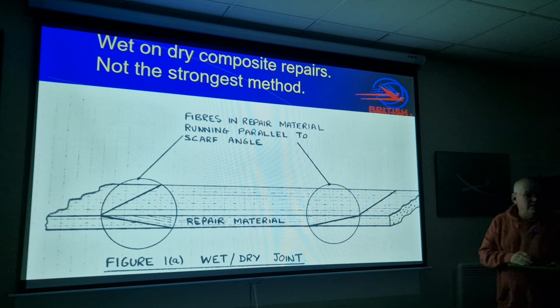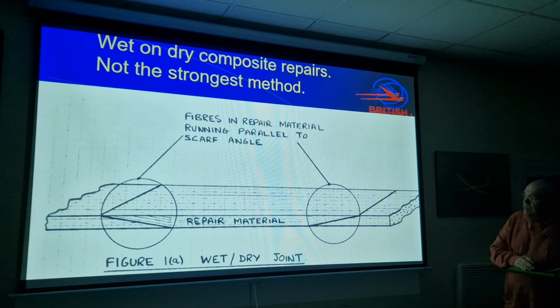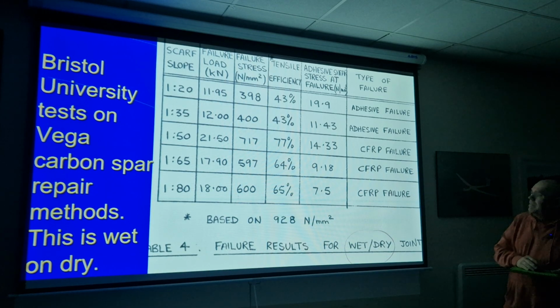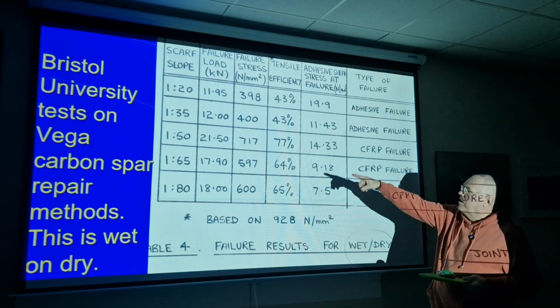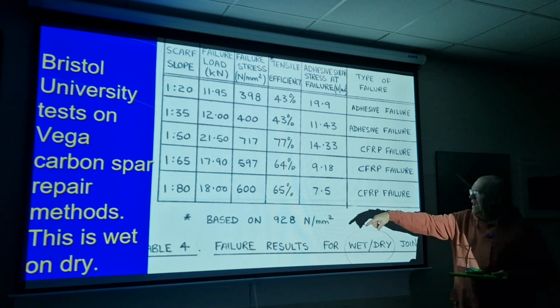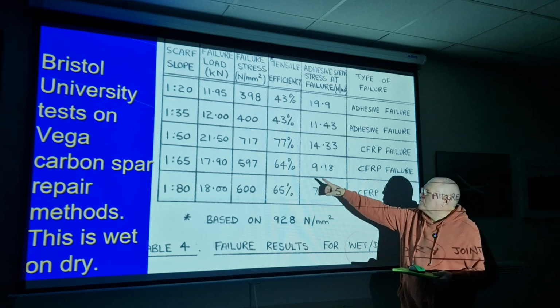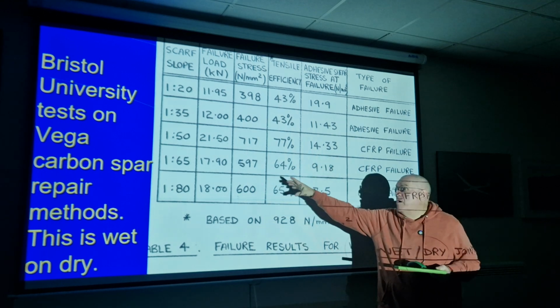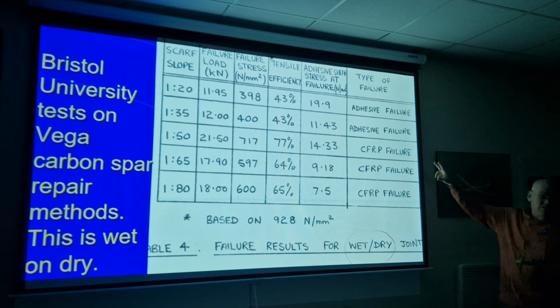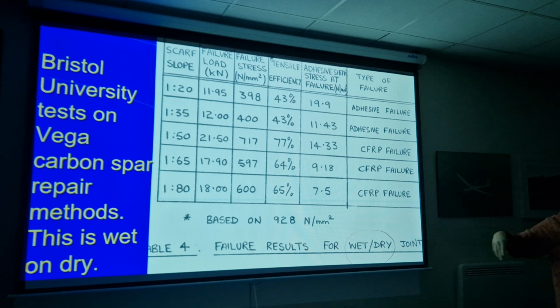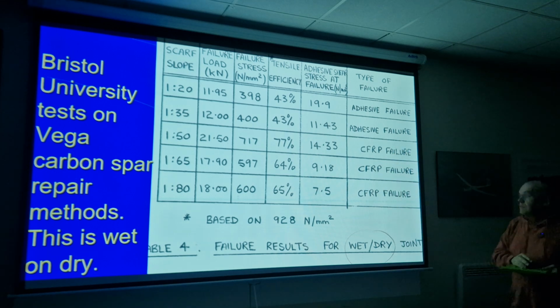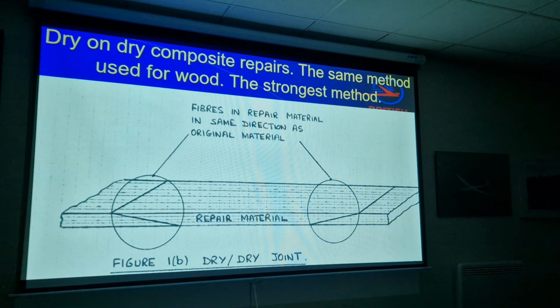But back in about 1980, when it came to glass fibre, Bristol University actually did some formal testing. And these are the best strengths they were getting on carbon fibre at Bristol University. At 50-to-1, they could achieve about 77% strength. But bear in mind, they were using Vega spars, which were very variable in build quality. They really were. So they actually gave up in the end and started making their own spars. So what they then figured out was,